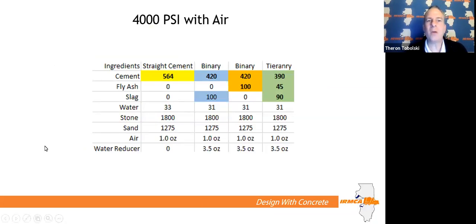When we talk about concrete mixes, there's a couple different ways that a concrete producer or the engineering industry can allow concrete mixes. The first column you see is straight cement. So we have 564 pounds of straight cement. There's no fly ash and slag. And then we have water, stone, sand, and air. This is for a 4,000 PSI entrained air mix.